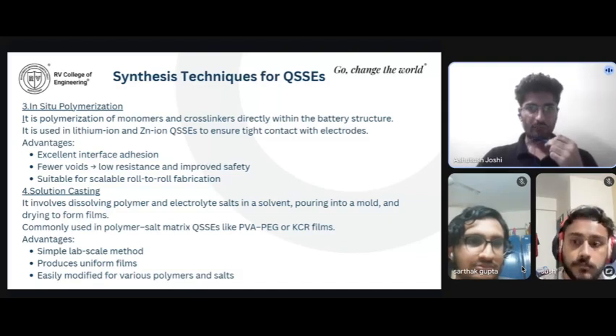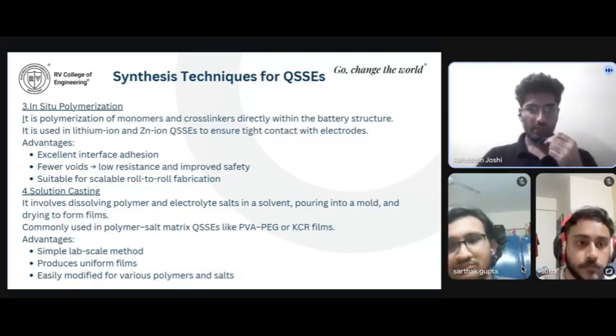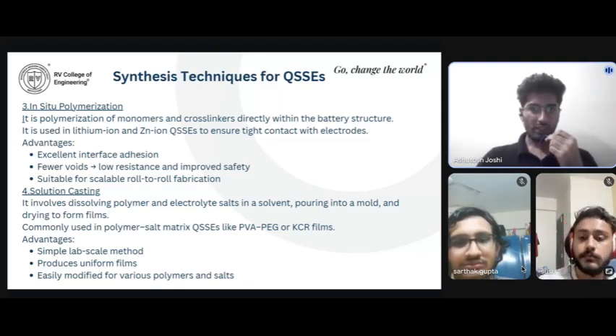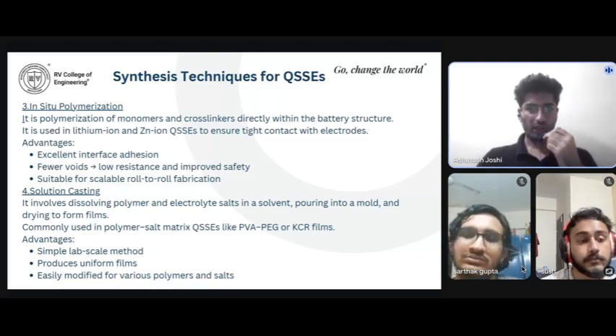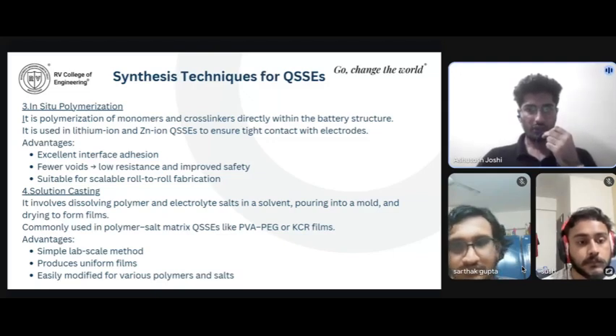Then fourth, we have solution casting. Solution casting is one of the most straightforward and commonly used techniques in laboratory-scale synthesis. It involves dissolving a polymer in a solvent along with an electrolyte salt such as LiTFSI. This solution is poured into a mold or flat surface and allowed to evaporate slowly, forming a thin film. Its applications include polymer-salt matrix QSSEs, including systems like PVA, PEG, LiCl films, and biodegradable QSSEs. Its advantages are that it is simple and cost-effective for lab-scale testing, produces homogeneous uniform films with good ion conductivity, and is easily customized with different polymer salts and even fillers like silicon or graphite. Next slide.